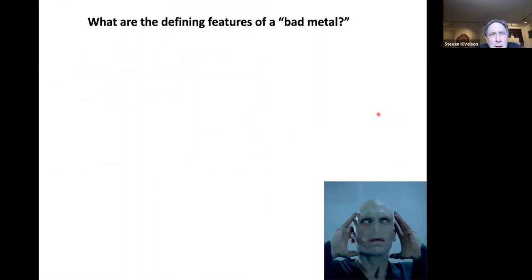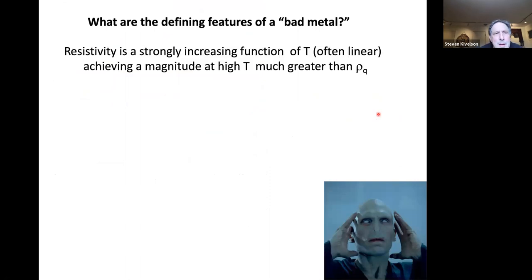So what are the defining features of a bad metal? There's a resistivity that is a strongly increasing function of temperature, often linear, which achieves a magnitude at high temperatures that's much bigger than the quantum of resistance.